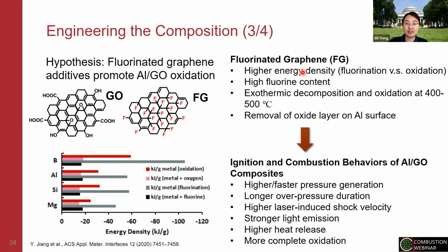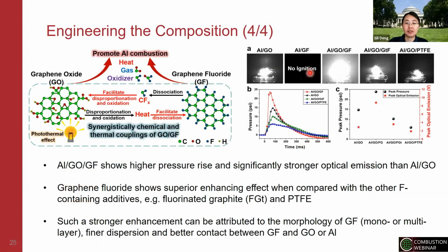So our hypothesis becomes, if we put some of the fluorinated graphene additives into the system, we will expect to see enhanced ignition and combustion properties of the previously synthesized aluminum and GO composites. And indeed, we can justify our hypothesis in the experiments. And to our surprise, there is a synergistic effect by combining the GO and the GF. So what does that mean is after putting in the graphene fluoride, the performance of the final composite is better than the composite of aluminum GO or aluminum GF.